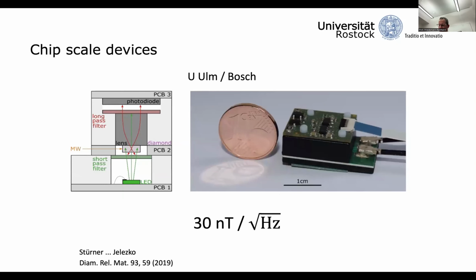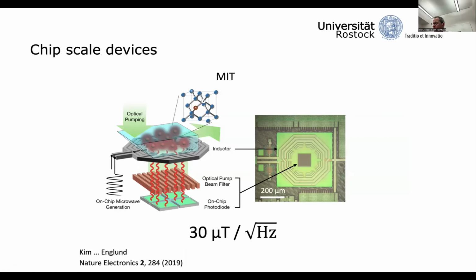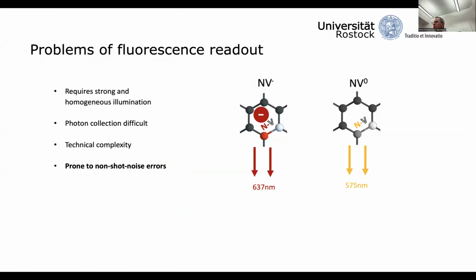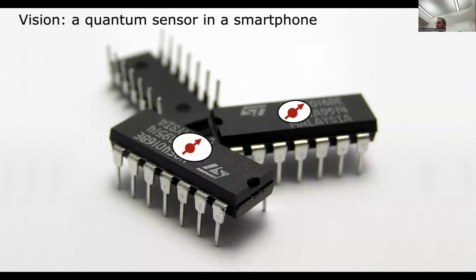It gets even worse when we look at chip scale devices. These picotesla per root hertz setups are typically large lab scale devices. Once we move into compact integrated setups in a centimeter-sized physics package, that performance degrades to the nanotesla range. And if we reduce it even further to an integrated circuit style package, as has been done by the lab of Dirk Englund at MIT, then that performance degrades to the microtesla per root hertz range. So clearly, one big dream of really having a competitive, sensitive magnetic field sensor that could go into an integrated circuit and possibly into a smartphone has not yet become reality.